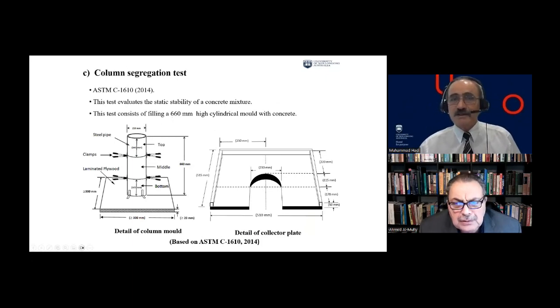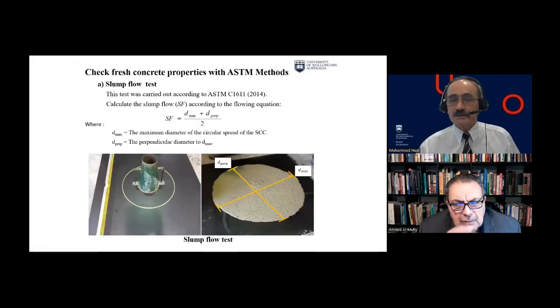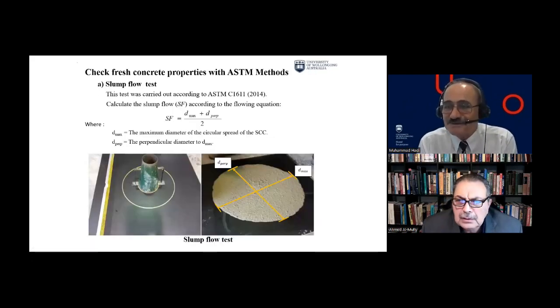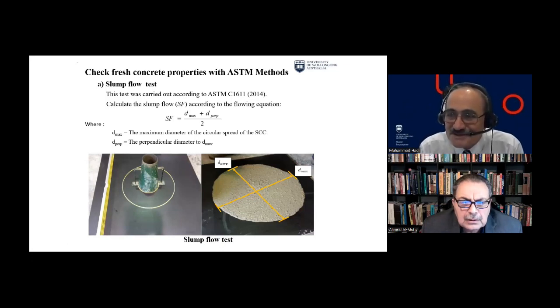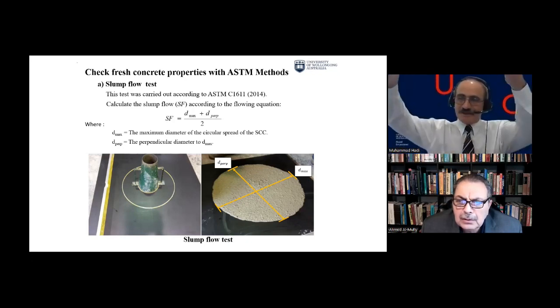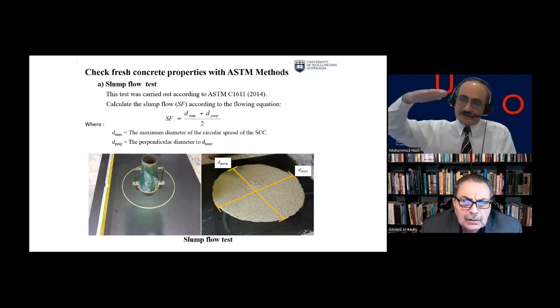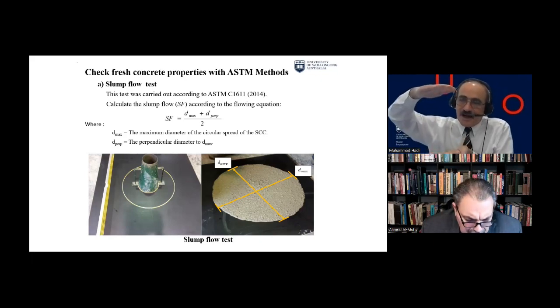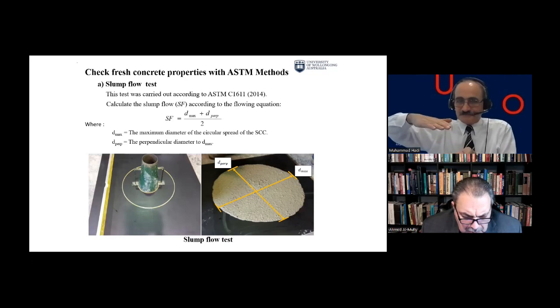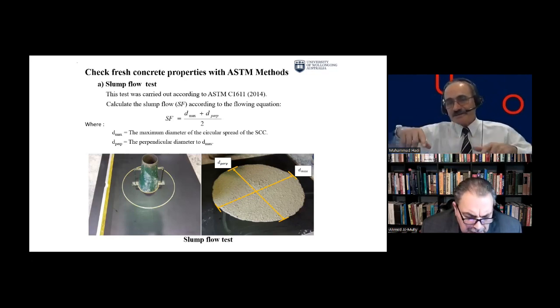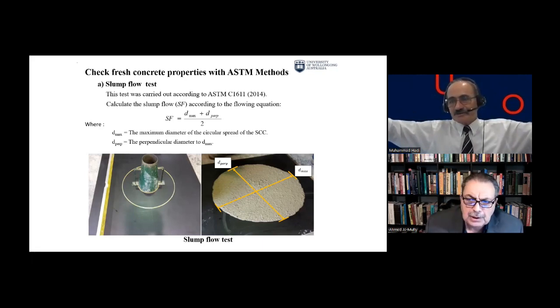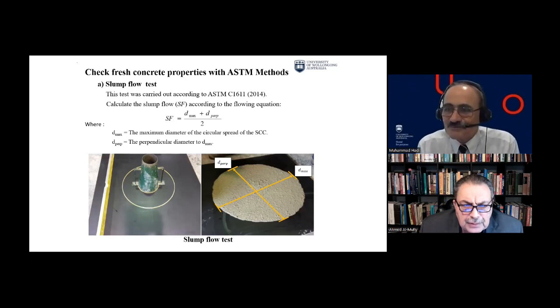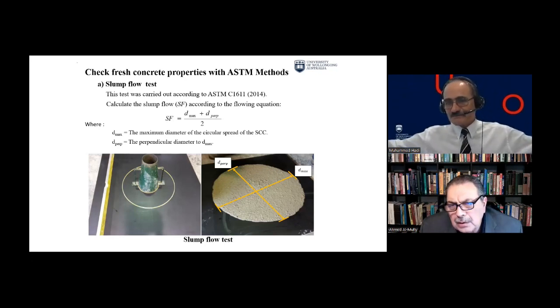The more is, why is the slump cone reversed? Why is it upside down? With self-compacting concrete the slump is like this. It is not bigger to smaller, it is this way. And with the usual slump, we measure the height, how much reduction happens in height. Whereas this one is the flow. So it will go, we read the diameter. We leave it, and then we read. So this is one test.